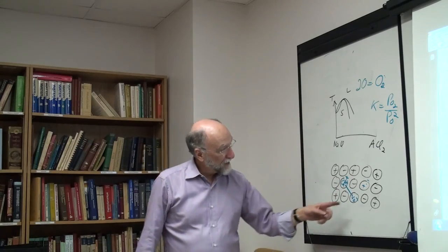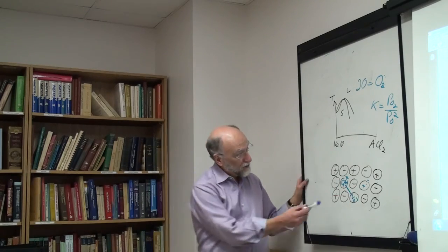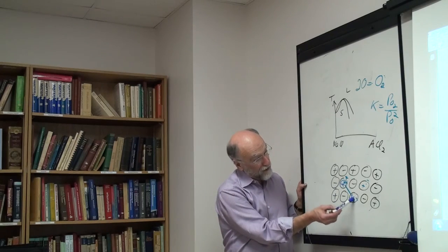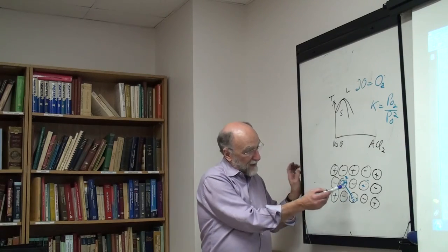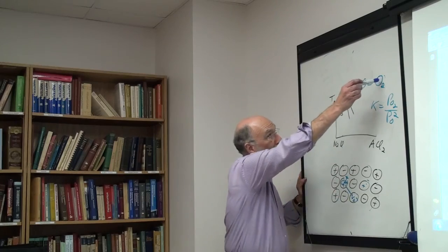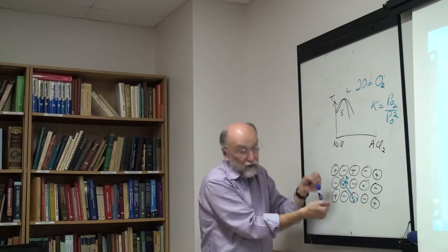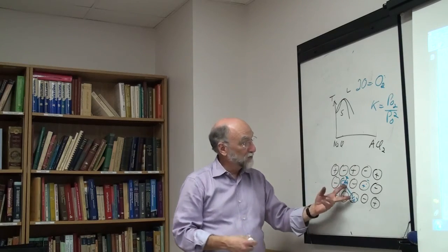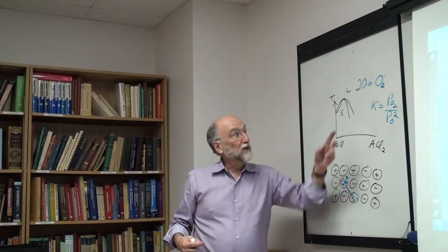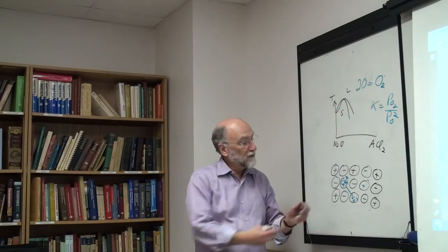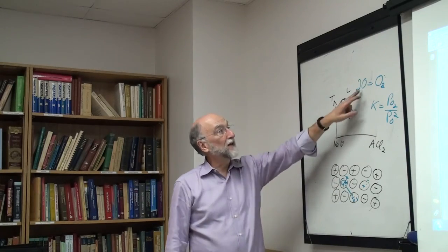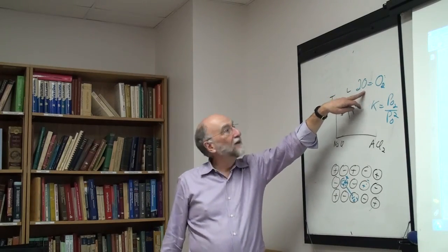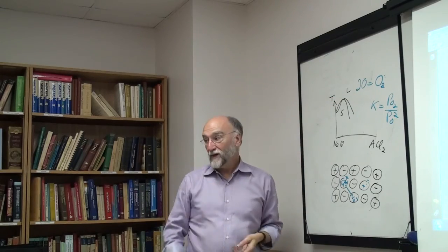That's exactly the same thing here. If you go to extremely dilute solutions, this is like a pair. This is like a molecule, calcium vacancy. This has a negative energy, just like O2 has a negative energy. So they're going to try to come together. And if you have lots of calciums and vacancies, most of them will be forming pairs. Just like most of your oxygens will form O2s, but if you have a dilute enough solution of oxygen, they're going to fly apart and not come back together again.